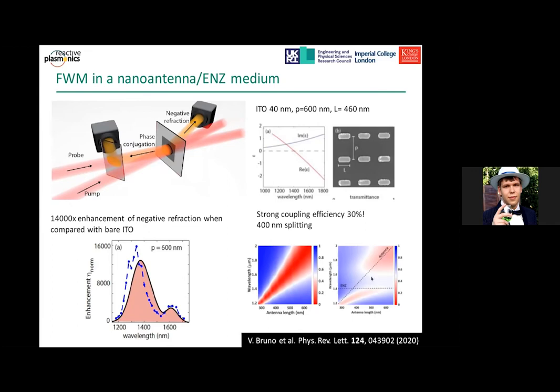And in this condition, we assess the structure by using the four-wave mixing process, a degenerate four-wave mixing process, in a geometry that mimics negative refraction. The geometry is shown here on the slide. And we've seen that in the strong coupling condition between the epsilon near zero and plasmonic resonance, we observe the 14,000-fold enhancement of negative refraction as compared to the bare ITO.